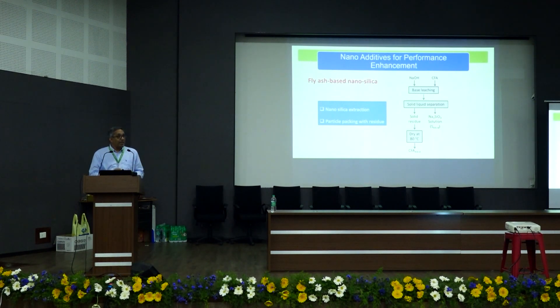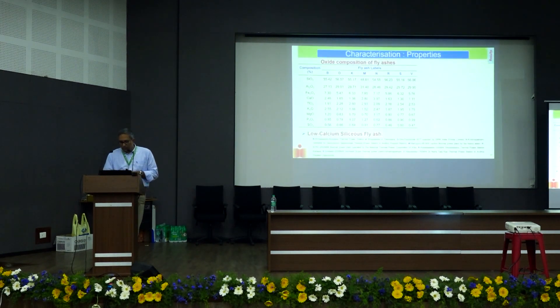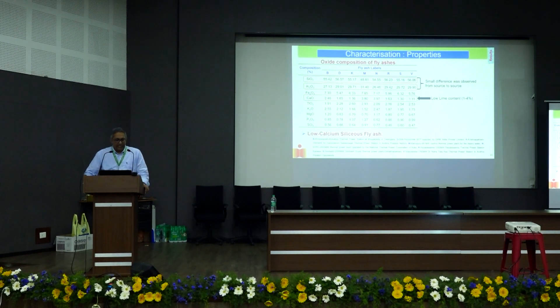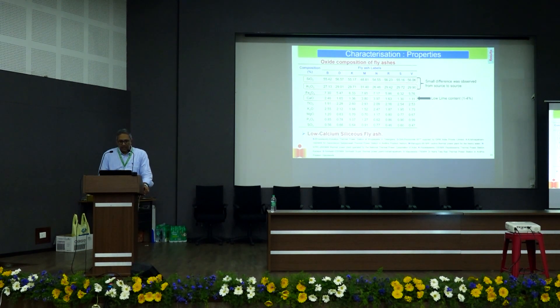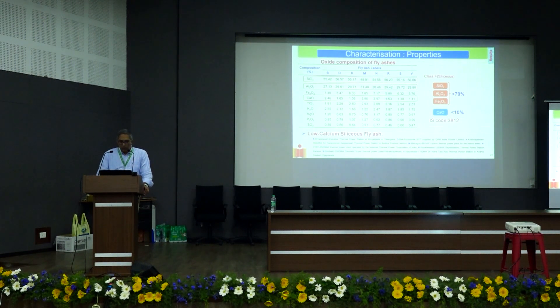This started about 10 years ago when we collected fly ash from close to 50 sources. We found that the oxide compositions from XRF evaluation look pretty close to each other — typically, most of our fly ashes from north and south of India have about 50–55% silica, about 20–30% alumina, and are very low in calcium. This is very typical of Indian fly ash, except for a few which are higher in calcium. Most of them meet our codal requirements.